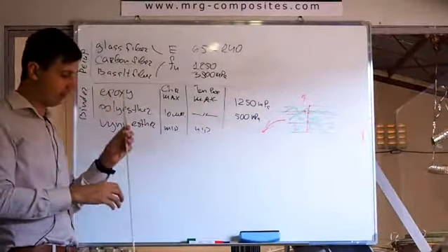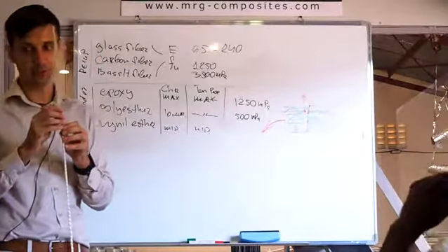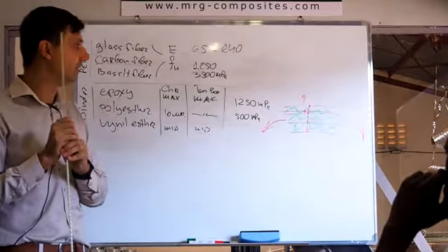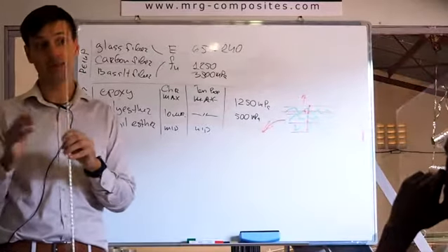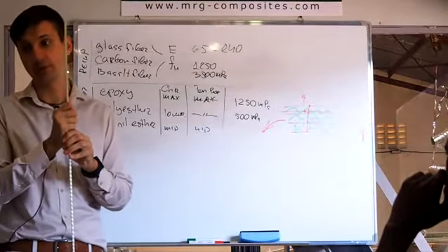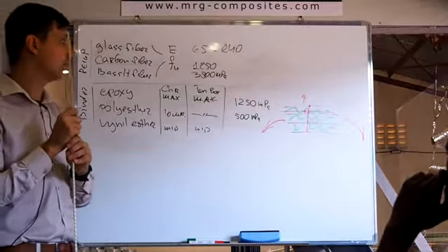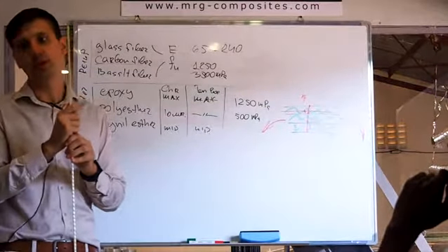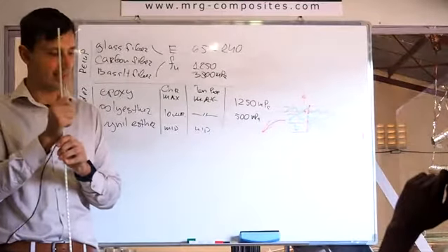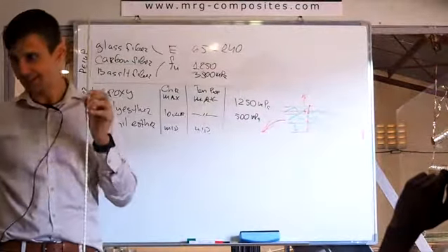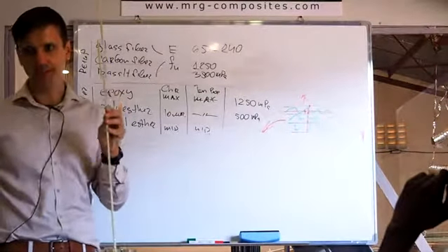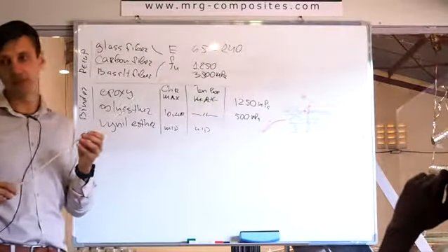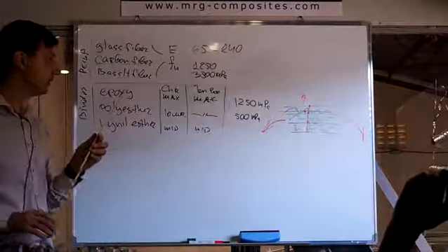So if you compare our bar made of polyester resin and made of epoxy, first of all, the tensile strength is going to be lower. Another thing, the lifespan for material made of polyester resin is going to be lower. Why do we have to talk about it? Because within some time, I don't know, 1 year, 2 years, we're going to get competitors here who will offer material that looks like this. The price is going to be lower, but you have to know that the quality is going to be much lower. And it is strictly prohibited to use this material where this one is recommended. This is a pretty important moment.